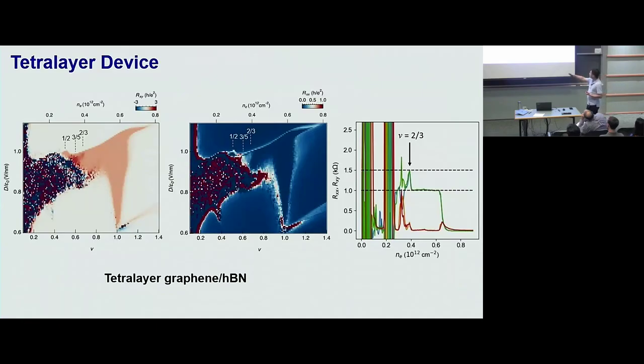Again, if you just look at this base temperature big phase diagram, you get the impression, oh, this integer extended quantum anomalous Hall state is taking over everywhere. However, if you look carefully, there's still color indicating Rxy more than h/e². Okay, 2/3, 3/5, they are still there. And if you really look at a line cut, you see this 2/3 still touches 1.5, which is 3/2 h/e².